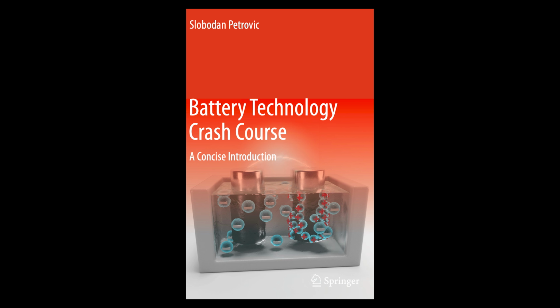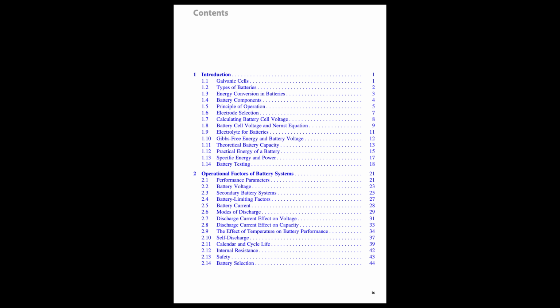And finally, NiCd components and failure modes. Components can vary, different electrode constructions, sintered, pocket, etc. Separators, usually polypropylene or nylon. Failure modes. Internal shorts are common, sometimes from those cadmium dendrites growing through the separator. Electrodes can passivate, become less reactive. Active material can degrade or shed. Separator can break down. Sometimes the positive electrode swells. Various ways they can wear out.